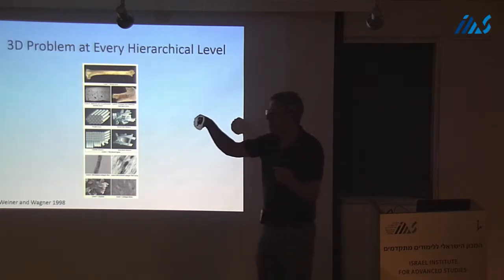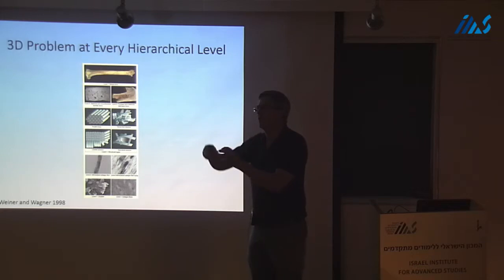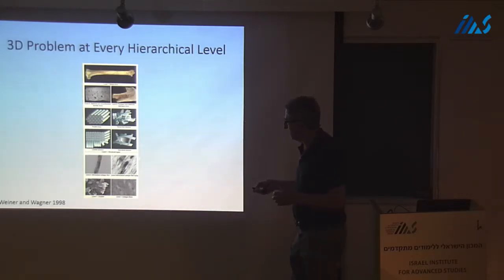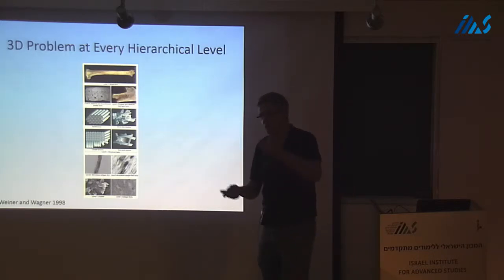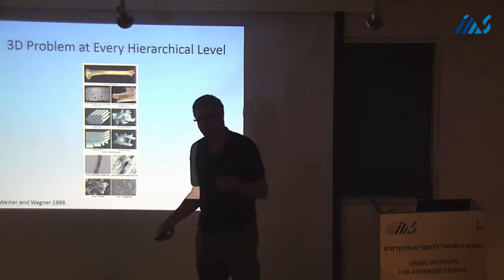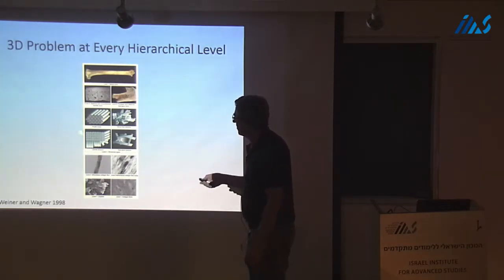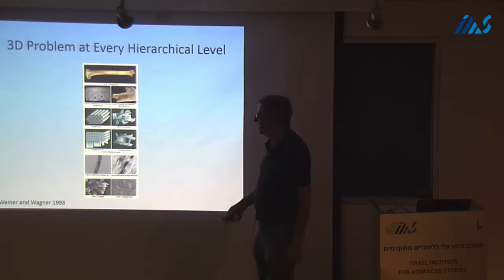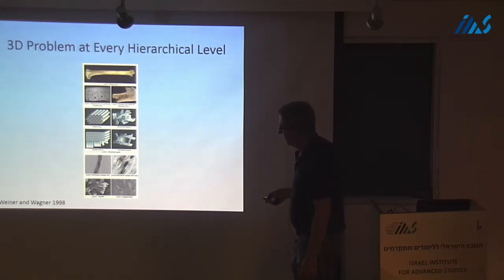By that I mean if you start at level one, these are the components of bone, the crystals and the collagen. Then you go to the building block of bone, which in this particular scheme we published in 1998, I called the mineralized collagen fibril. You take those fibrils and put them together in some sort of organizational motif. That's what we mean by the hierarchical structure of bone.